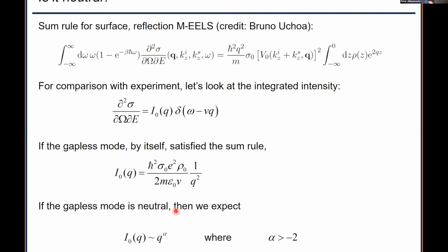So you could ask, does this excitation violate the F-sum rule? It's a simple question of asking, what is the intensity of this thing doing as a function of Q? And does it follow what you expect from the F-sum rule, or does it do something faster than that? There are some subtleties that come up because we're actually measuring a surface response function. It's not a bulk response function measurement. So we're measuring the chi double prime of the surface. To understand this, you actually have to derive an F-sum rule for that surface response function.